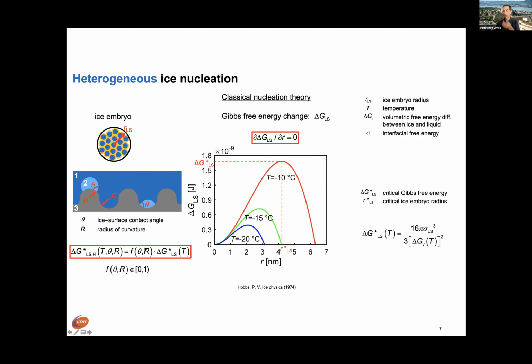And if one wants to retard ice nucleation, one has to make this function f, which I do not show explicitly, as close to 1 as possible, so that the energy barrier would be as large as possible and ice will not form for as long as possible. So that is a little bit of background on ice nucleation. I want to add only one little thing. As these embryos are generated, of course, they release their latent heat. So it is a process where you have a very low temperature, embryos are generated, locally generate some heat, and life goes on.